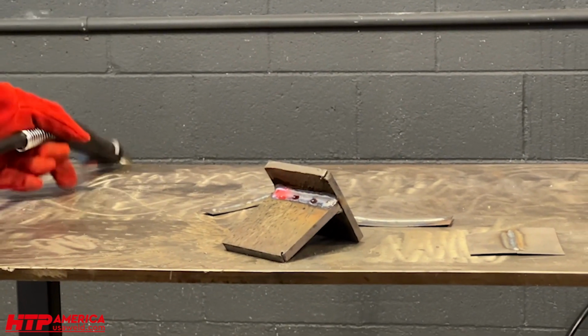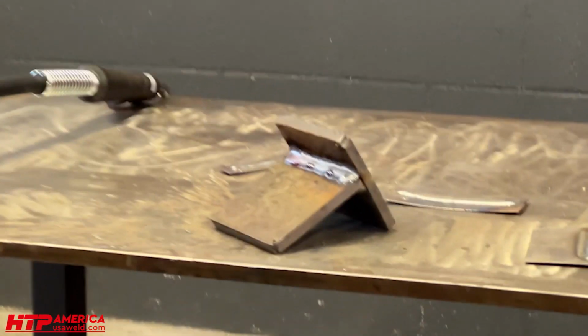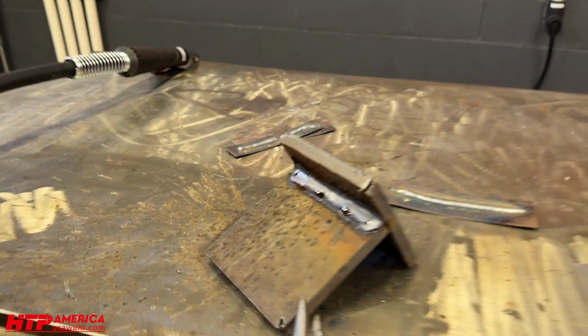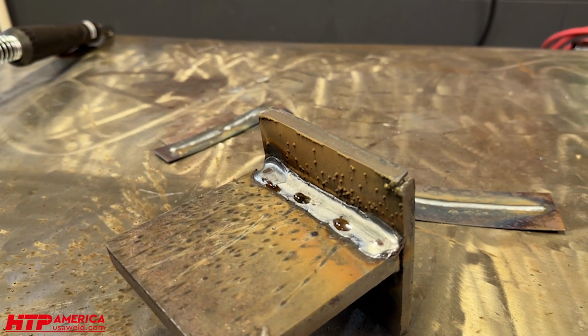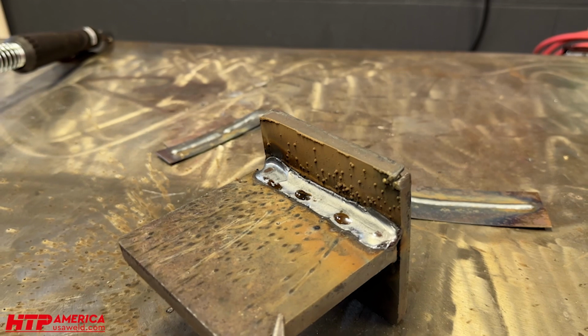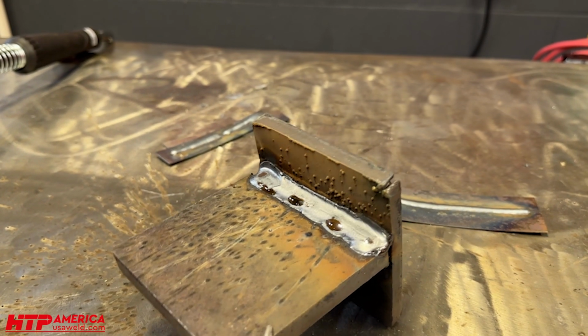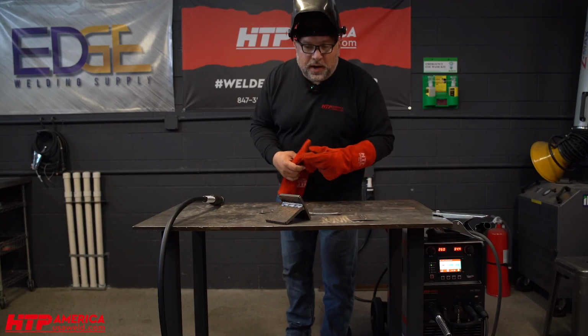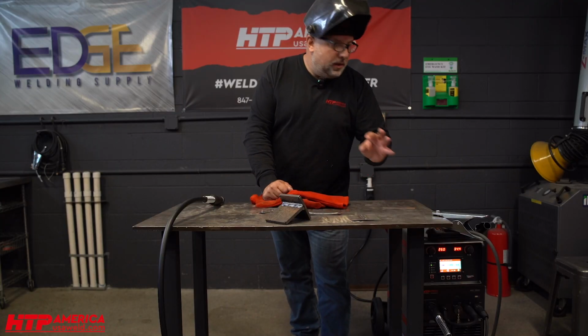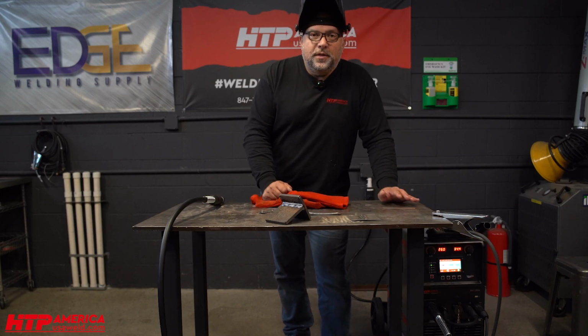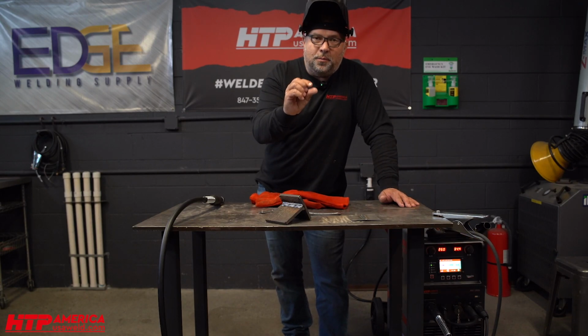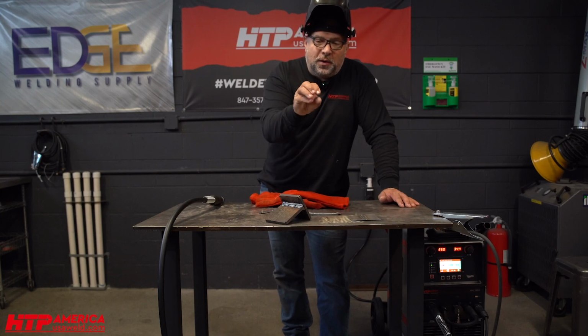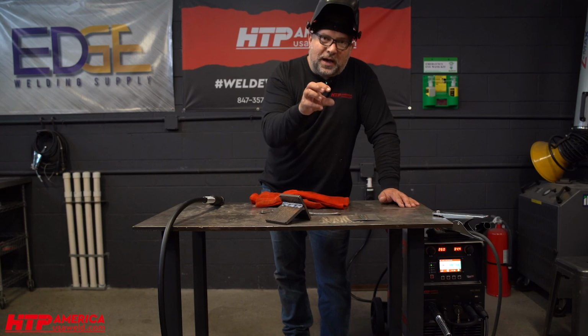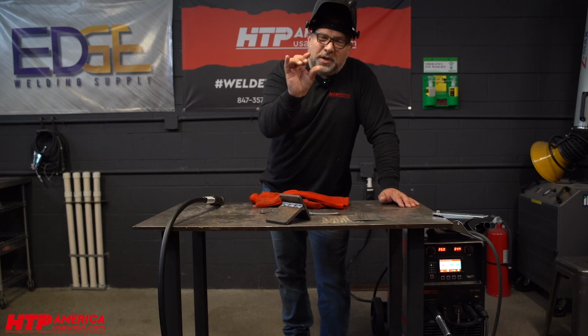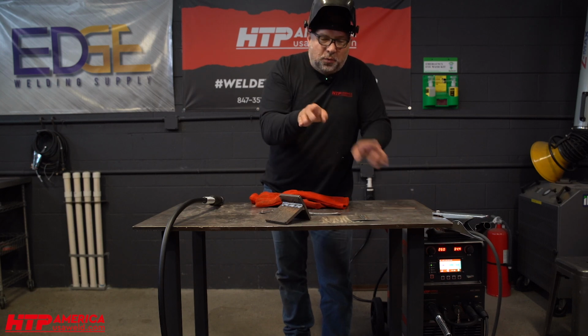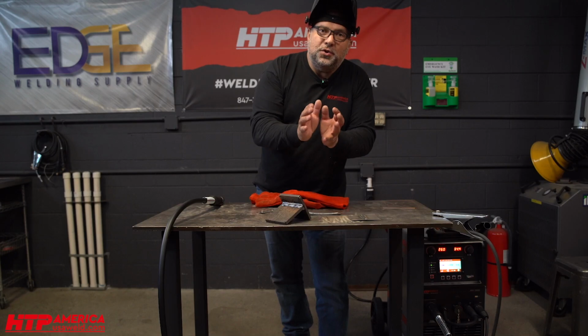So that one went in really nice. No undercut, fewer BBs. I kind of had my gun angle figured out now. And the arc length was about right too. And once you're in spray arc, your voltage deviation, your trim, like your number you dial in with your right dial, that is the one that determines your arc length. More voltage is a longer arc, more swirling around, wider, less penetrating, wets out, maybe nicer, but your goal should be to trim the arc down, shorten it up to where it's nice and focused, where you don't heat up the whole part, you just heat up your weld joint.